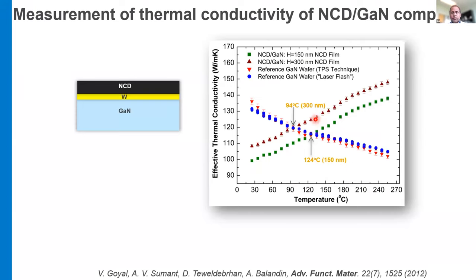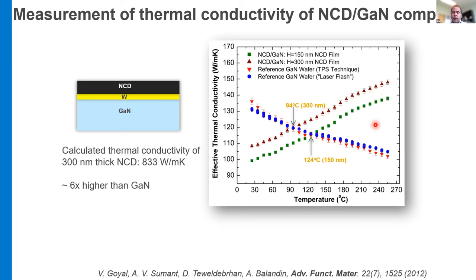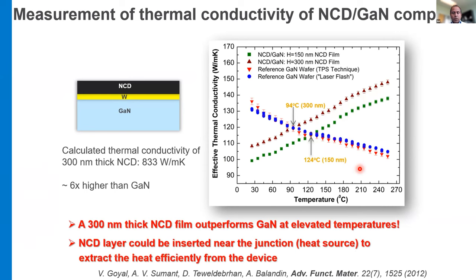So what essentially it is showing is that even just a 150 or 300 nanometer film, you are effectively getting very good thermal dissipation, which is about six times higher than the gallium nitride. And even if you increase to a little higher, you can increase the thermal dissipation much more effectively, because what is important is that when the device is getting heated because of the higher power dissipation, you need a very good thermal conductivity. So using this process, maybe you can think about depositing this nanocrystalline diamond near the junction, where there is more heat dissipation source, and then effectively you can use it for dissipating the heat properly.